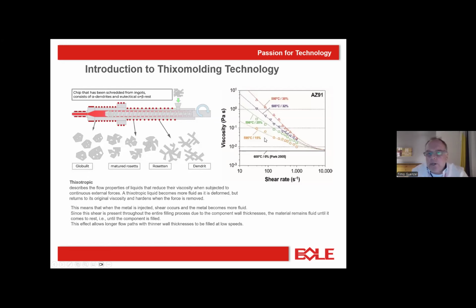Here you see on the right side the chart. There was a question in the meeting about the temperature and the solid share. You see, when you have AZ91 and run with a temperature of 595 degrees, then you have around 50% solid share inside. When you run the same material AZ91 at 580, then you have around 38% solid share. That means when you have AM60, the temperature range is plus 20 degrees, and when you have AM50, then you have plus 30 degrees. And then you have nearly the same results.